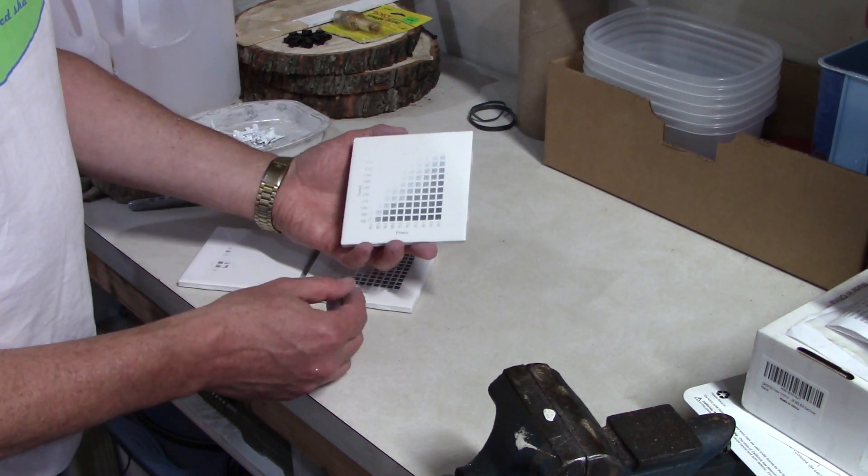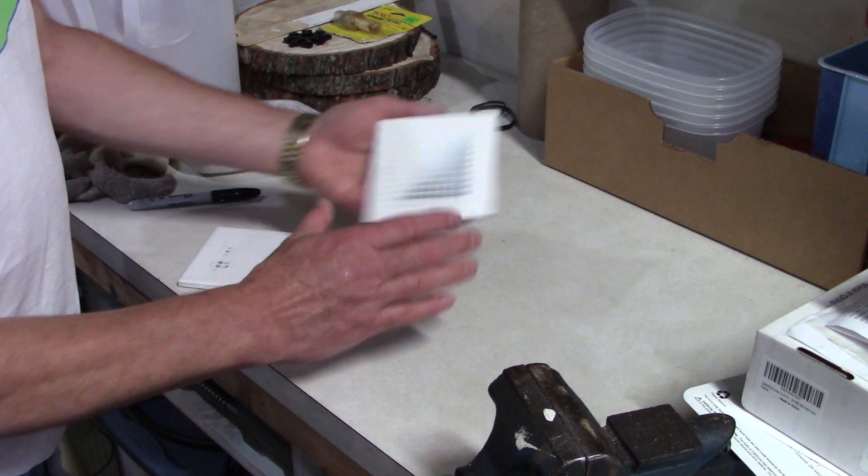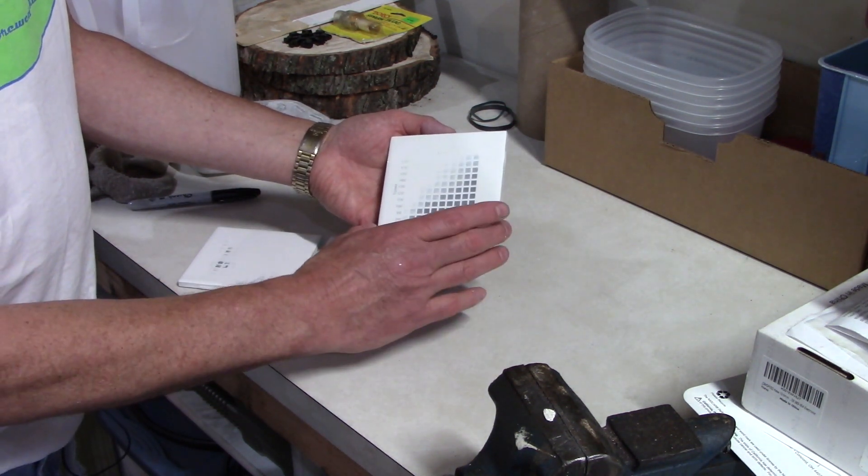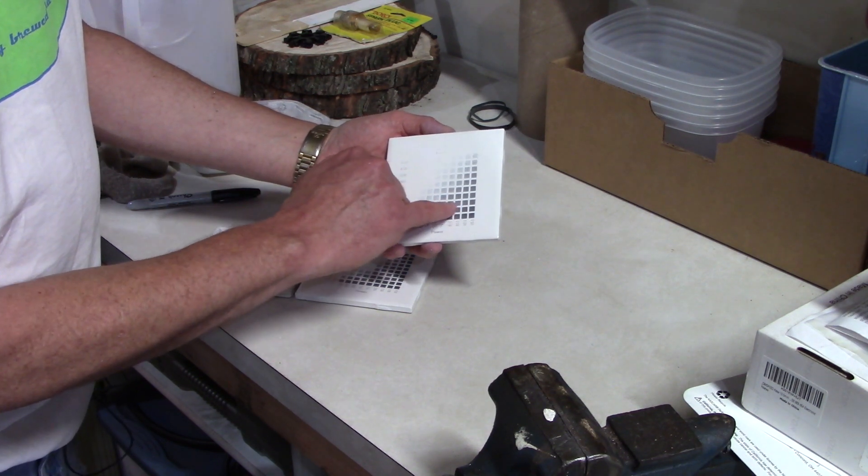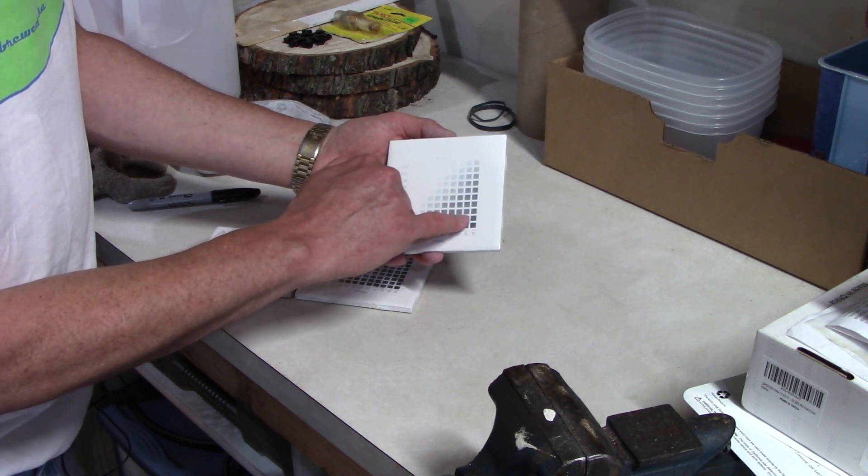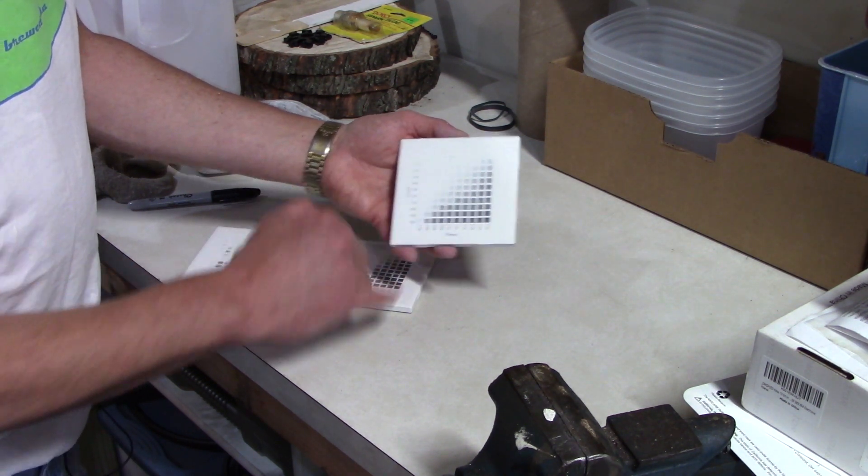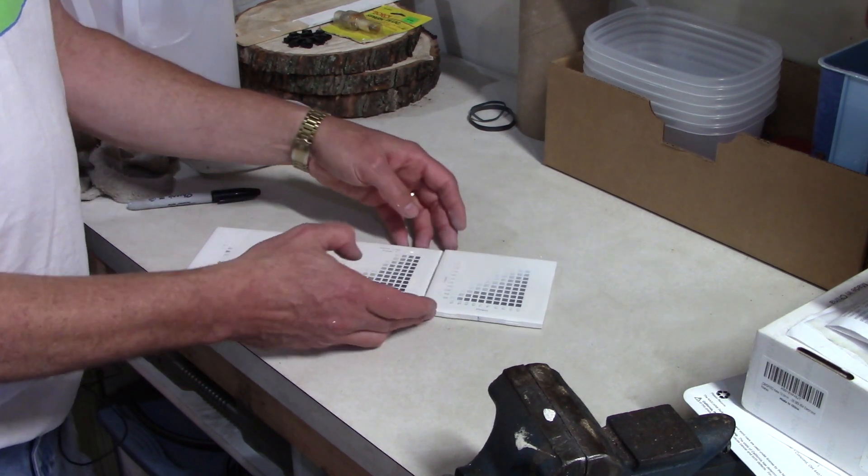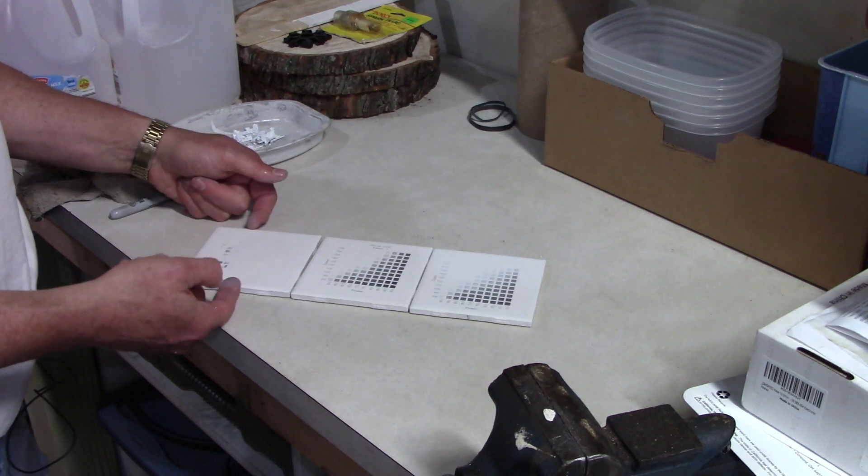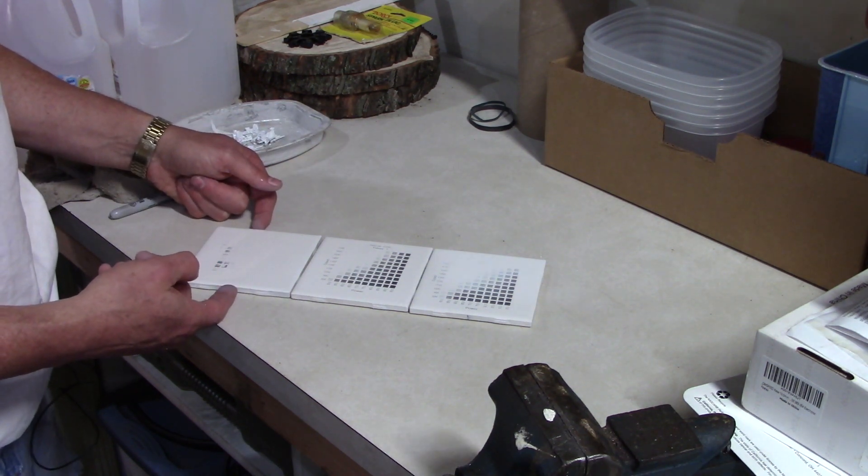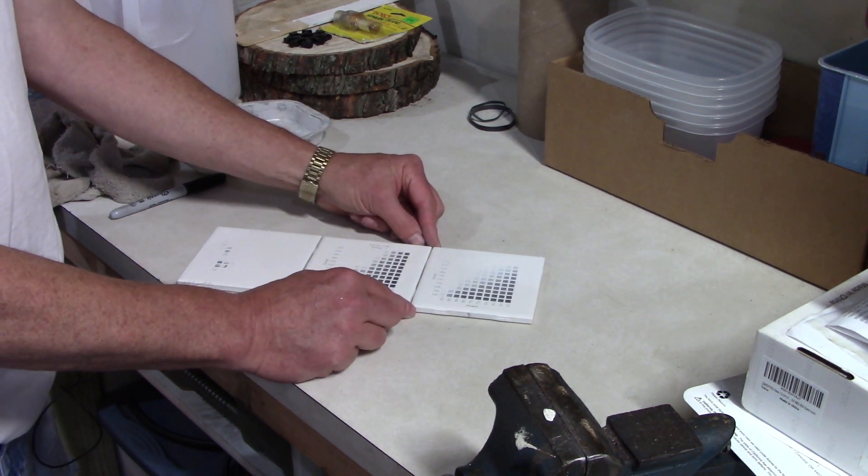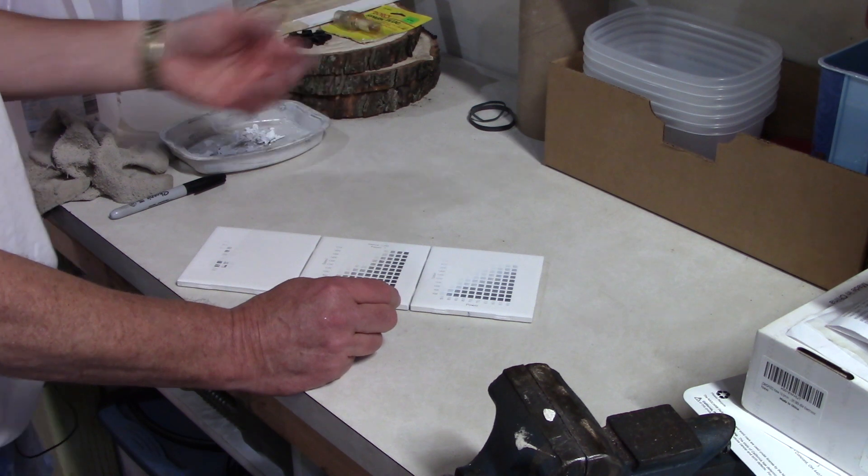And this one is kind of about the same. This was just the single pass. So it's just a light coat going back and forth in one direction. And so again, at 1000 at 85. It's a little light, but we still have some darker if we slow down a little bit and increase the speed. So somewhere around this amount of paint looks to be about the best. There's an issue if you get too much paint on there. And obviously if you don't get enough on there, you would run into the same thing. But a nice light coat seems to do the trick.